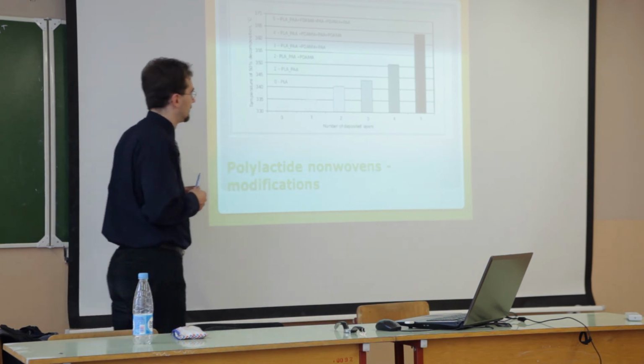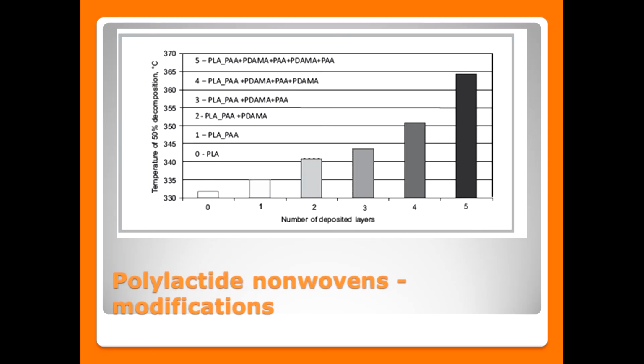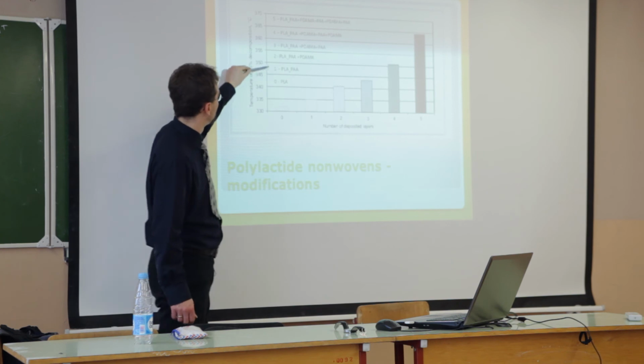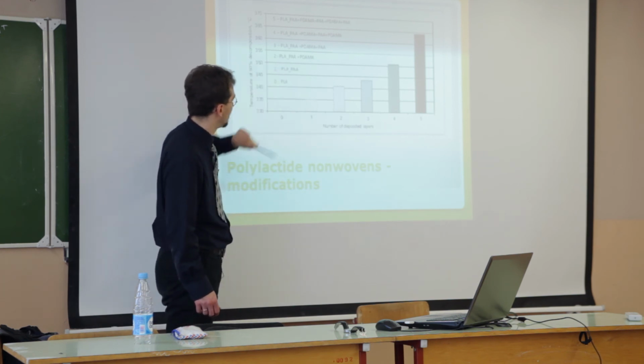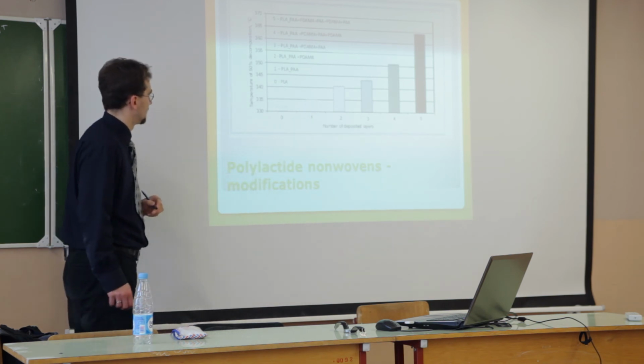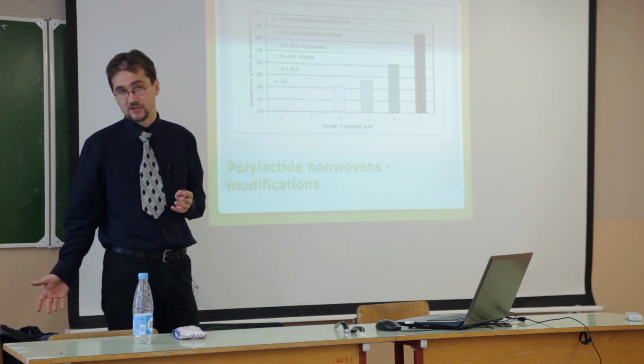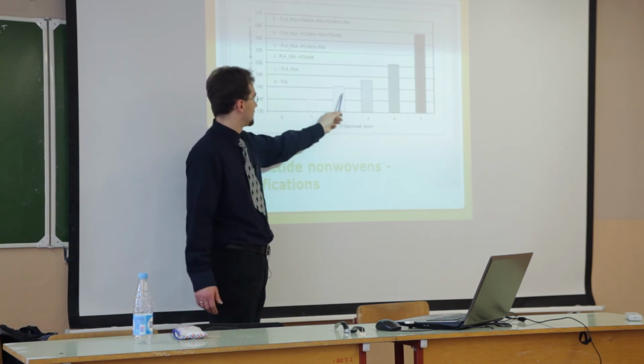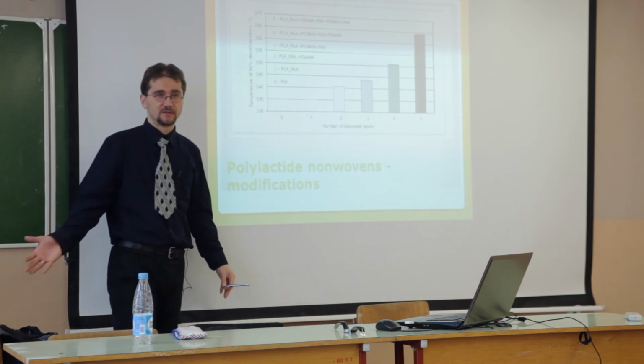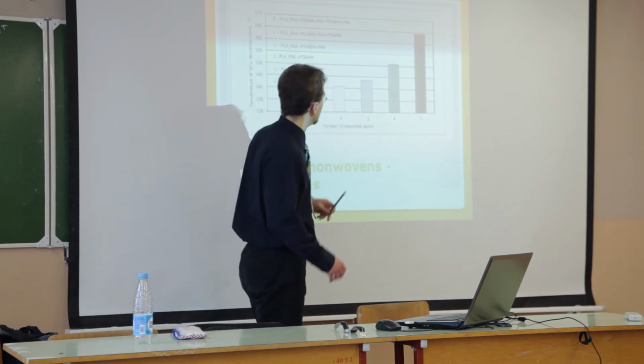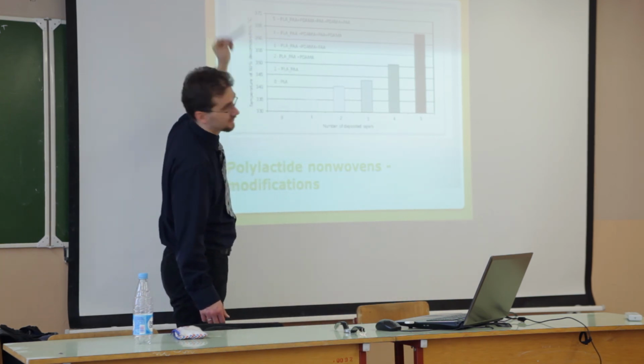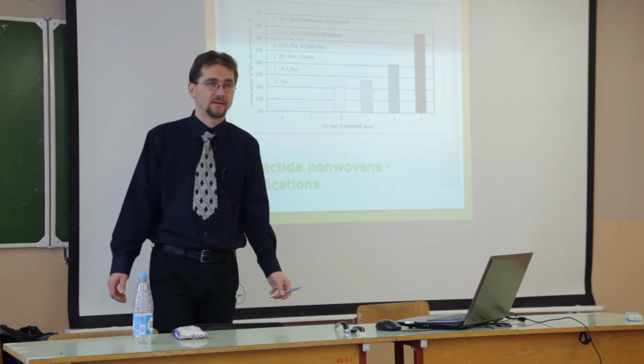But I introduced all samples into the TG analyzer, and the temperature of decomposition of the unmodified material is 332 degrees. Sample number 1 is after grafting, this is PLA with PAA, and here the decomposition temperature is 335 degrees, so it changed by a couple degrees. When I analyzed the sample with 2 layers, the temperature of 50% decomposition was still bigger, and finally the difference between the unmodified sample and the sample with 5 layers was about 33 degrees, which is quite a big difference.